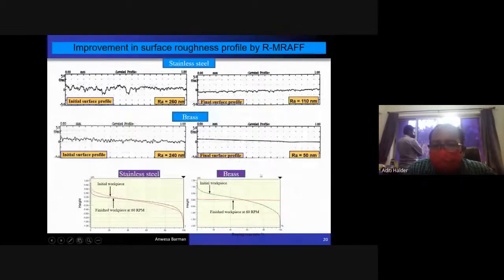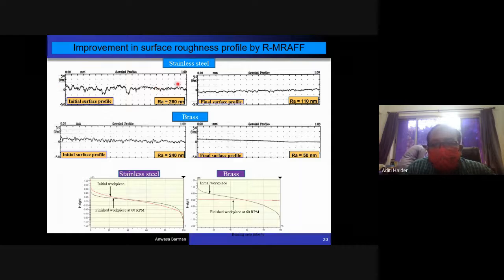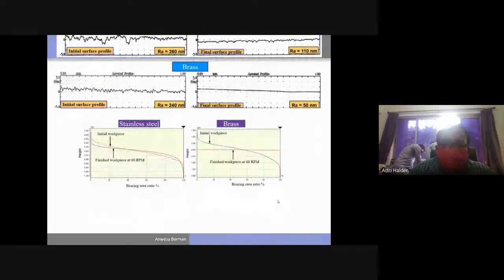Now coming to the surface roughness profile. This is the initial surface roughness, which is about 260 nanometer. It is not smooth here, but for stainless steel it is almost finished, and for the brass workpiece it is almost flat. This is the bearing area curve. When two surfaces are meeting together with a high relative movement, the bearing area curve is very important. In the initial bearing area curve there is a higher slope, but in the final bearing area curve you can see the slope is almost reduced. Now it has become almost flat here.